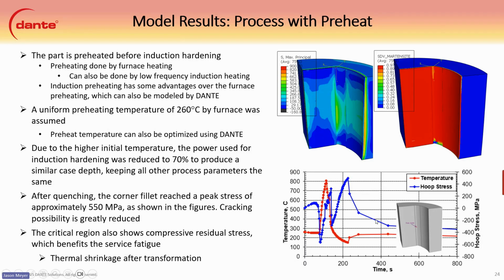The reason this one goes down into compression here is because the whole part was preheated, so the whole thing has to shrink down thermally, and when it does so, it increases the compression, and it turns this part back into compression. That compressive residual stress is really good. It benefits surface fatigue, and it really helps with wear on the coupler itself. So you really want that before the process, we believe. And that's, again, caused by the thermal shrinkage after transformation.